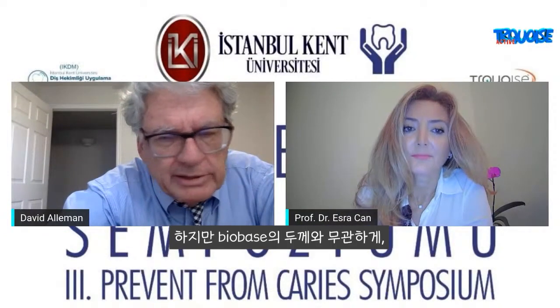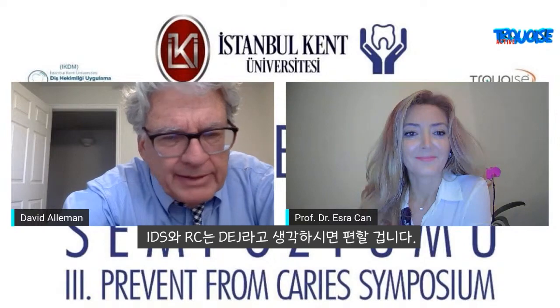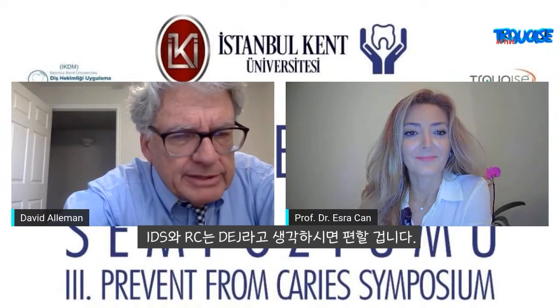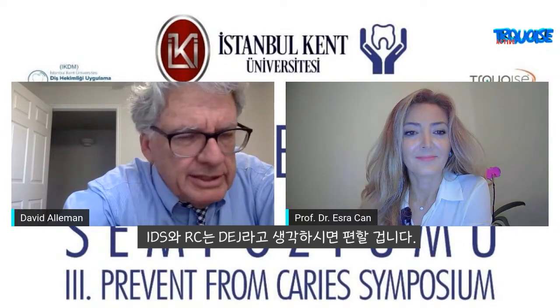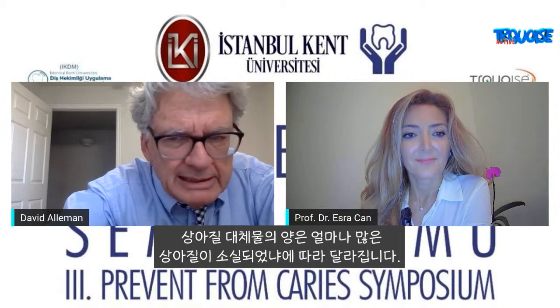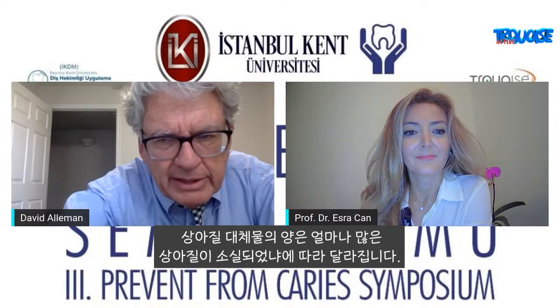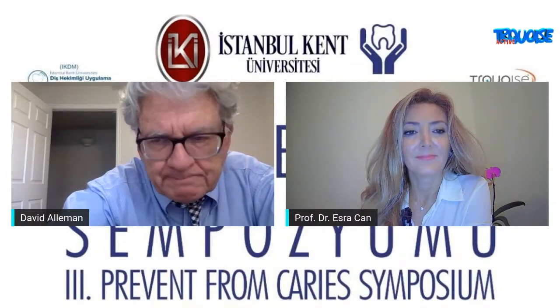But the first layers of immediate dentin sealing and resin coating, that's in place in every biobase, no matter what the thickness is. So think of the biobase as the dentin replacement, and think of the immediate dentin sealing and the resin coating as the DEJ replacement. And so every biobase has the foundation of a DEJ replacement, and then the thickness of the dentin replacement will just depend on how much dentin is missing.